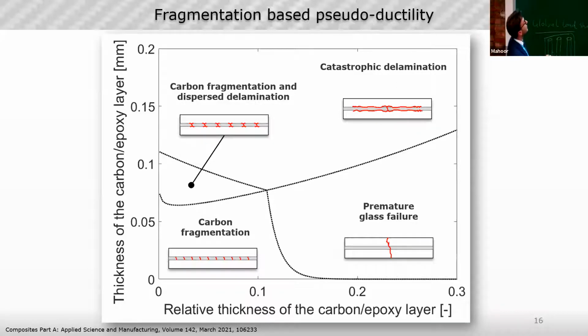With this study, we have 4 different scenarios. Actually, they are 3, because this could be considered in common. But this is the worst, of course, which is the premature failure of the glass. As soon as we have the fracture of the carbon, the glass fails as well. So the glass should be designed in a way that after the fracture of the carbon, we have a strong enough layer of glass to carry the load. And designing the glass in a proper way leads to this area. So as you can see, we are moving towards a thicker material in general, and that could be considered an issue from a practical point of view.